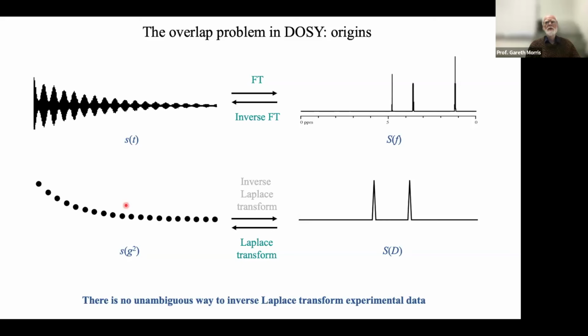Okay, well, here are two reasonably different, well-resolved peaks, but there's hardly any difference in the decay. And at this point, we begin to think, oh dear, let's have a broad distribution. Again, the differences in the decay are there, but they're tiny. Too broad, and at this stage you say, oh dear. It really is a real problem. We've got all these different possibilities, but they're all consistent with our experimental measurement.